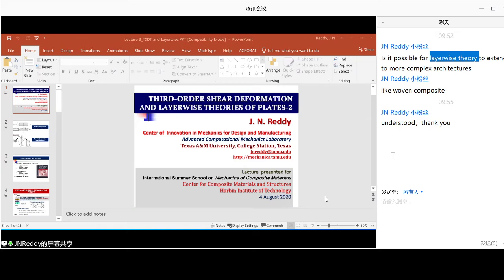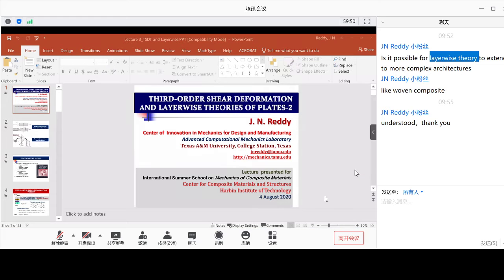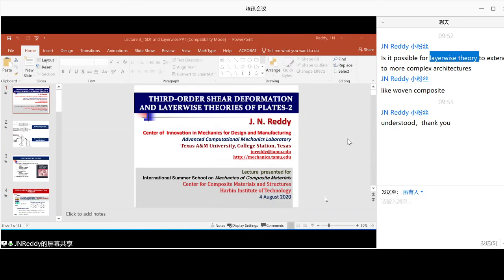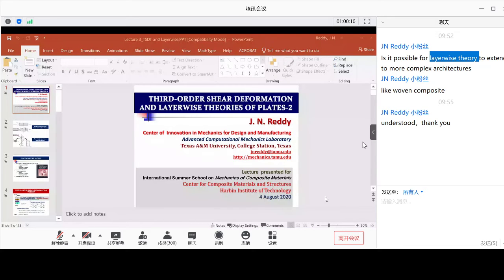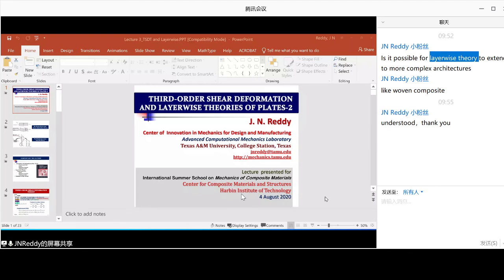That is again a very good question. We have done that. Remember I talked about this phi function through the thickness, phi of z. That function becomes a discontinuous function. We put a Heaviside step function wherever there is delamination, so the delamination area is represented differently.